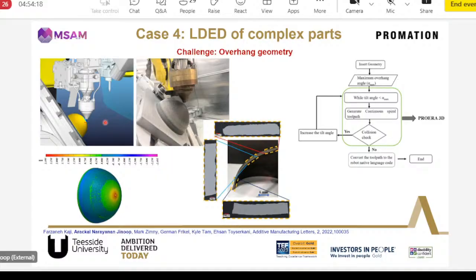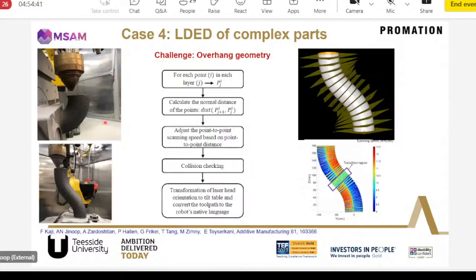So we developed the process methodology for that. Then we characterized them completely. We could find that these are highly dense in structure, and the geometrical variations are within plus or minus 0.5 millimeter, which is acceptable for that particular application. And then we went on to make the spherical tanks as well. Then we also worked on developing overhang geometry. So this was a work that we published in Additive Manufacturing Journal.